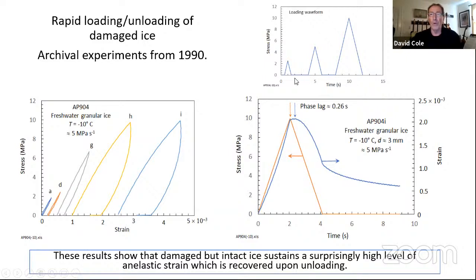And just briefly, what we're looking at is the stress applied to the sample is a ramp at a given rate. It's either 5 or 10 megapascals per second, applied periodically to the sample at increasing peak stress levels. So just ramp up, ramp down, wait a bit, ramp up, ramp down, et cetera, et cetera. And there'd be a lot of intermediate load ramps in between times. And down here, what we see is the stress-strain response.